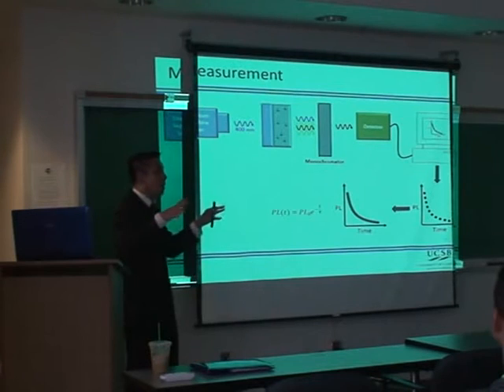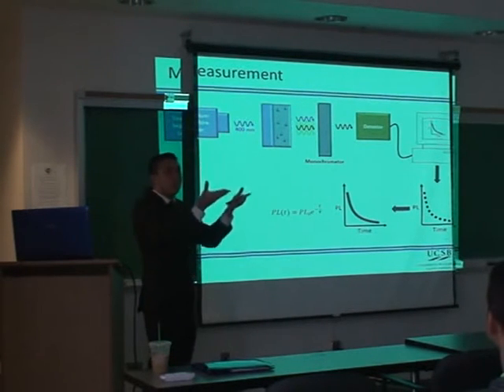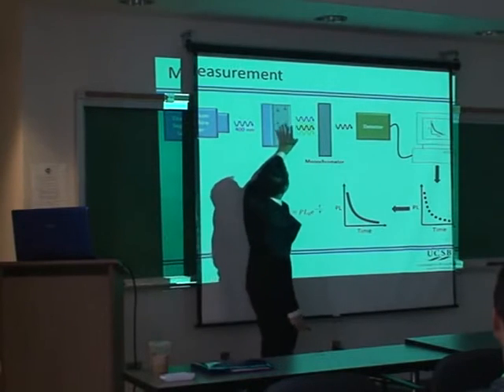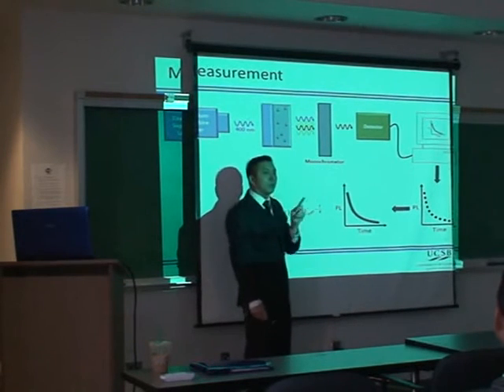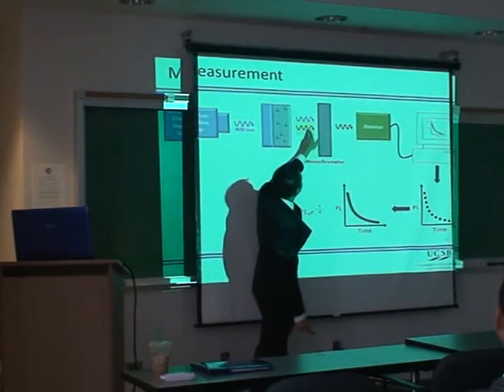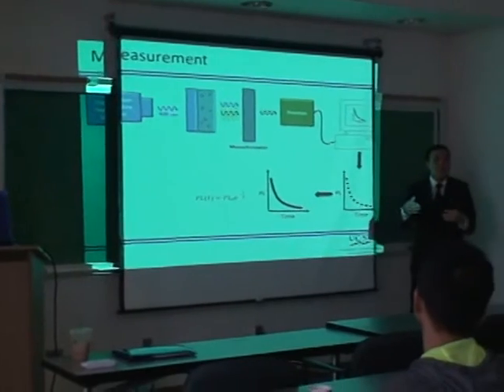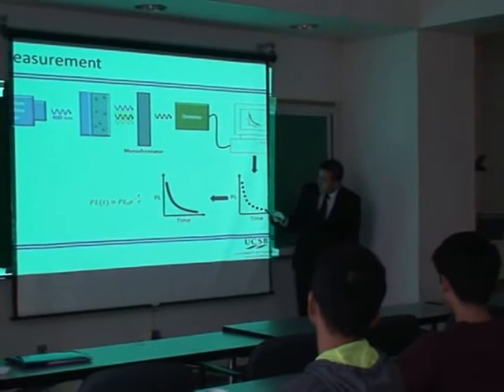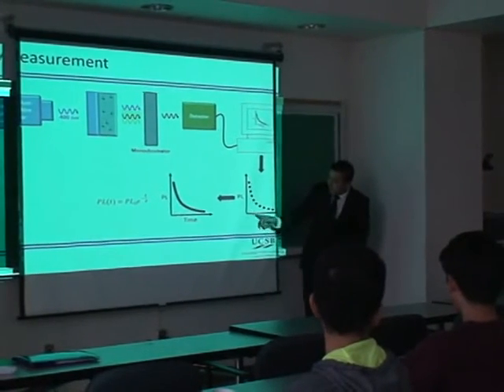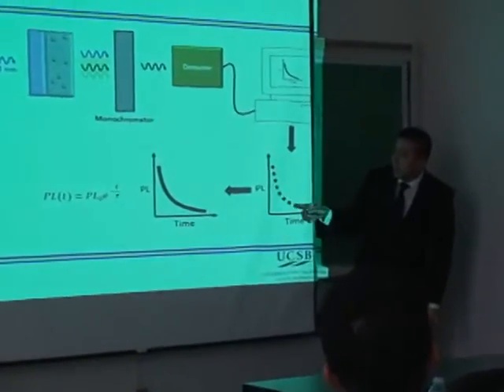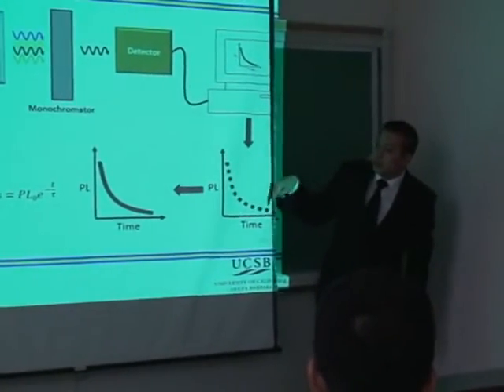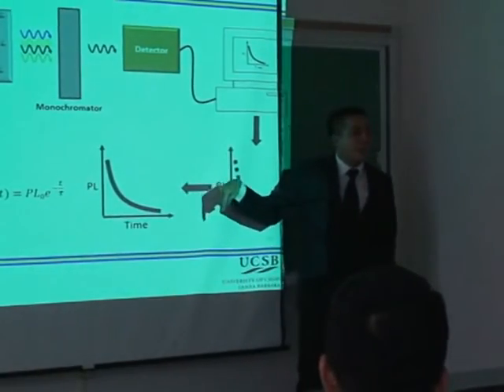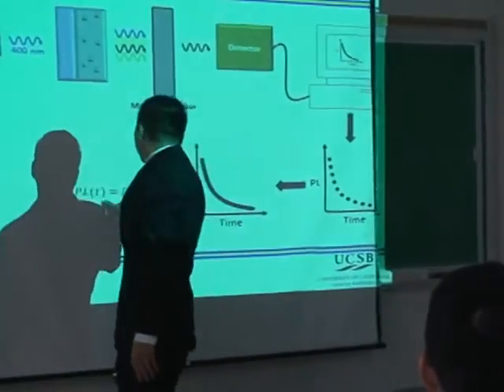So at time 0, you have this population of excitons, and then they'll gradually decay. As I mentioned earlier, when you have excited excitons, they can emit at different frequencies. But what we want to do is just record one wavelength. So we'll use a monochromator to select one of these wavelengths, and we'll turn on the detector. And this detector, instead of recording at different wavelengths, will actually record as a function of time. It will just sit there and wait as these excitons arrive. And what will happen is that we get these points appearing on this graph, with excitons appearing in the detector at different times. And if you were to connect all these points together, it would form this curve here, which is basically an exponential decay. And that can be fitted by a simple decay formula.